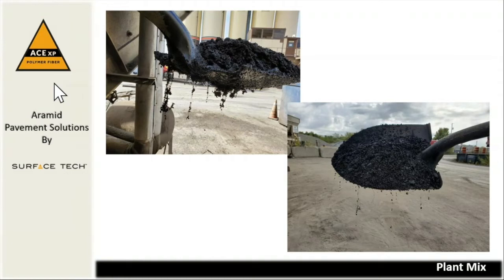When added or mixed correctly, the reinforced asphalt mix is easily absorbed at the point of discharge, as can be seen here. Improperly mixed asphalt is easily identified by the presence of mostly intact bundles, thus requiring an increase in the mixing time or a rethink as to where the bundles are being added into the plant.